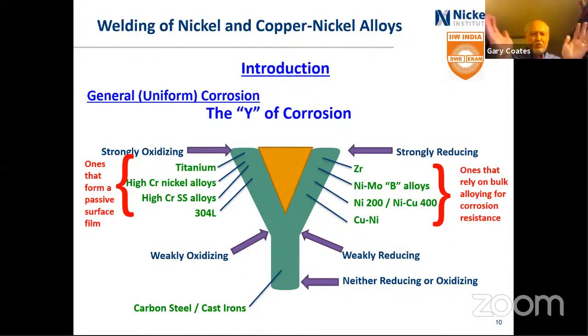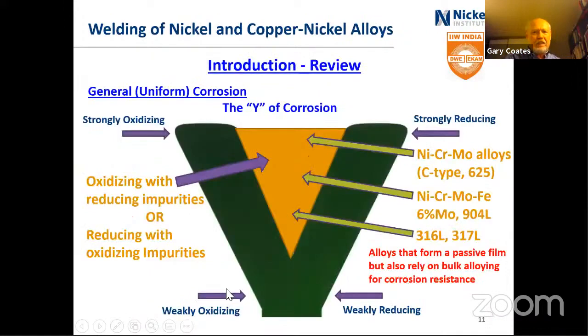Now, in the middle between the arms of the Y, we have an area that I call the middle ground. It can be oxidizing environments with reducing impurities, or reducing environments with oxidizing impurities. And this is where a lot of the nickel alloys fall, things like the C-type alloys, C276, C22, the 625, and we get into the high alloyed stainless steels, 6-moly stainless steels, 904L, work in slightly lesser conditions, and then 316L, 317L fall into an even lower level, but still they can tolerate some oxidizing conditions. They have that passive film, but they have elements like molybdenum that give it corrosion resistance to reducing conditions.